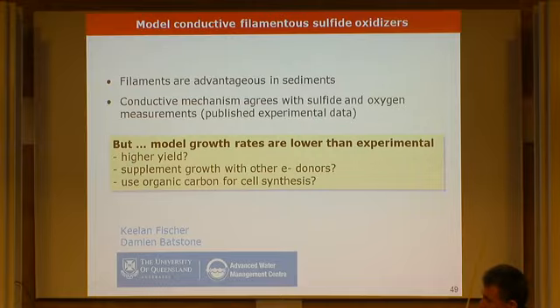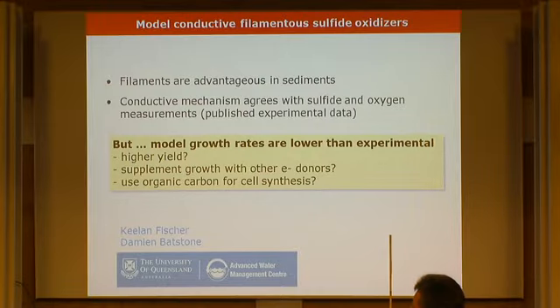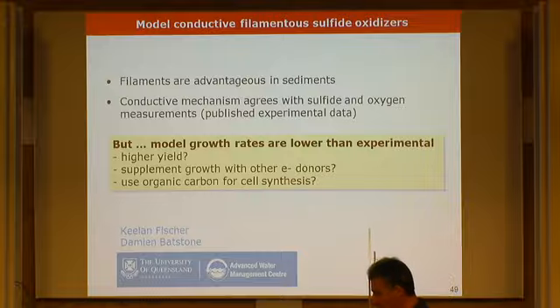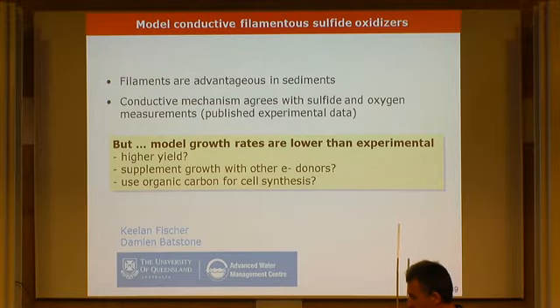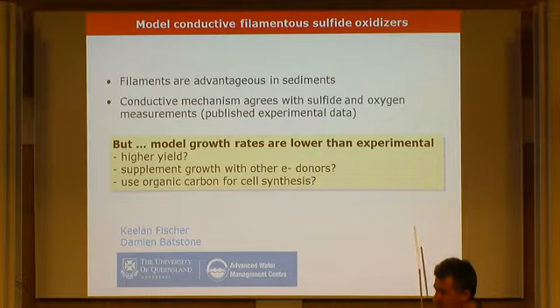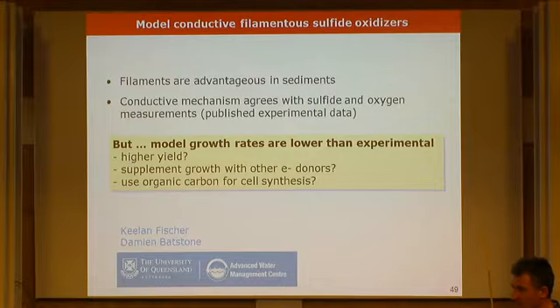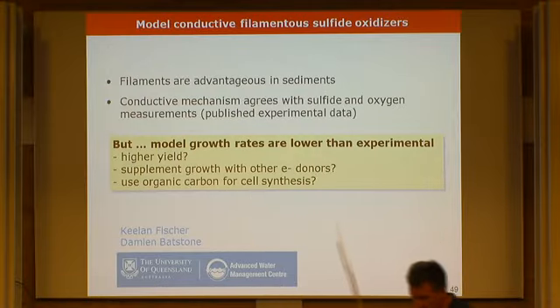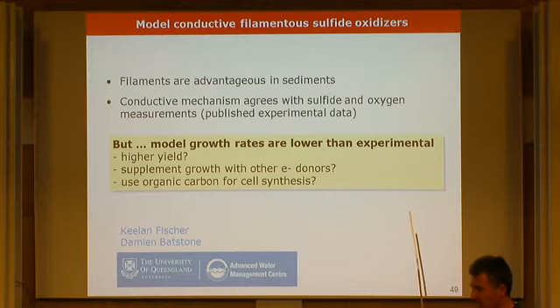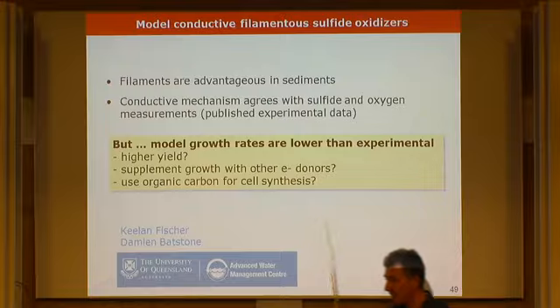May I ask a question? Yeah. If they would use inorganic carbon, then their inorganic carbon uptake would also affect pH, right? Yes. If you have enough inorganic carbon, it won't affect if it is buffered enough. But if it is only a small amount of bicarbonate, of course it will be consumed, and then you have larger pH drops. Okay, but in this case, the pH changes are mostly driven by the other oxidation. Yeah. And also, if you have organic carbon, also the oxygen consumption rates should change. Oxygen will oxidize this organic carbon.